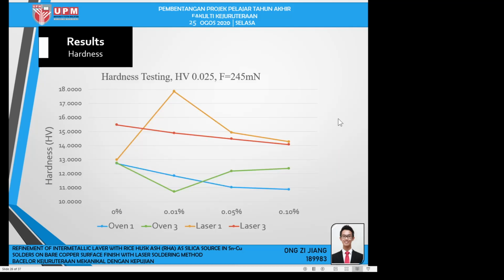Lastly, this is the hardness value obtained from the Vickers microhardness test. From the chart obtained, there is not much clear trend in the hardness value, but there is a very clear trend that the laser soldering method has a higher hardness value compared to the conventional oven reflow method.